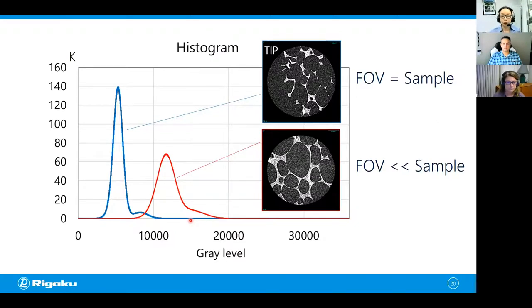This happens because when you have a bigger sample than the field of view, even if you don't care about the part outside of the field of view, those areas are still absorbing x-rays, reducing and also changing x-ray intensities. And that's why when you have a whole lot of volume outside of the field of view, you tend to see a higher level of noise. So you want to make your sample a little bit bigger than the field of view, but not 5 to 10 times bigger. You want that to be just right.